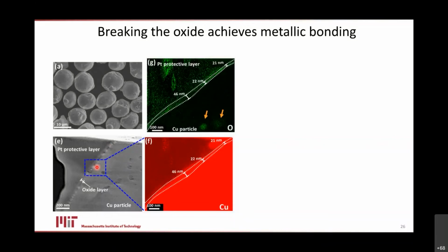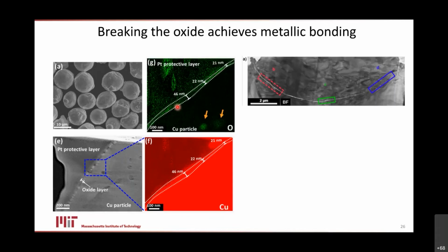Here we're cutting a particle open and putting it in the TEM, STEM and EDS. We're able to measure that the oxide layer we're up against on these particles is a thick, nasty layer, something like 20 to 40 nanometers thick. It's a big, thick copper oxide layer that is very friable, with a very low fracture toughness on the order of 1 megapascal root meter. So it's a flaky, thick, nasty oxide on these particles.